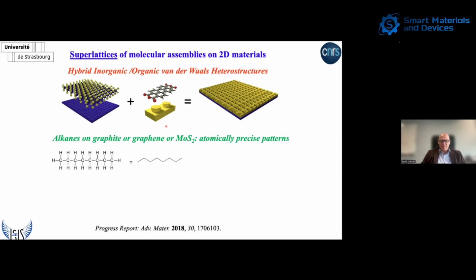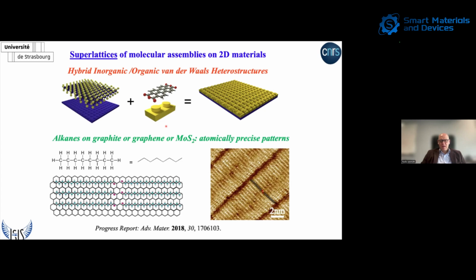Alkanes actually love the basal plane of graphene, which is the very same basal plane of graphite. This was demonstrated about 40 years ago by my former PhD advisor, Jürgen Rabe: you can assemble alkanes into a crystalline lamella structure on the basal plane of graphite, and you observe this by scanning tunneling microscopy. Why? Because alkanes love to physisorb along the zigzag axis of the basal plane of graphite, which is the very same basal plane of graphene. So you obtain this kind of crystalline lamella structure you can map with scanning tunneling microscopy.